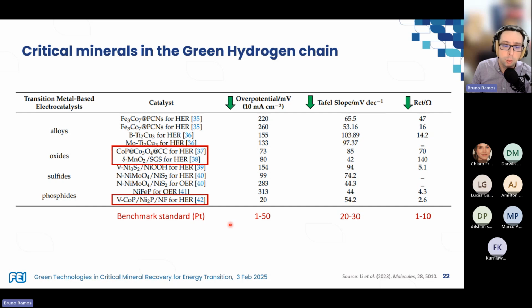So for platinum, for example, we have overpotential between 1 and 50. The overpotential depends, again, not only on the material, but also on the structure of the electrochemical cell. That's why it can vary from 1 to 50. The Tafel slope is between 20 and 30, and the resistance between 1 and 10 ohms. So we can see that the best guy here would definitely be these phosphides over here.